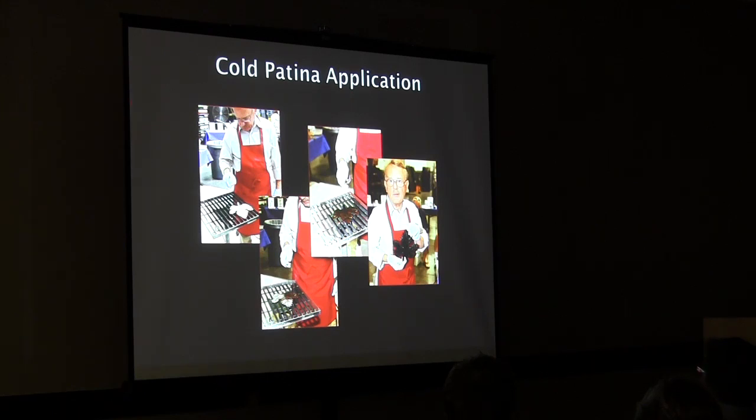And Black Magic is kind of nice because it's one of the many blacks, but it doesn't rust as quick. One of the things on steel and iron is that within 30 minutes to 2 hours, you've got acid combined with selenium. Those are the 2 main ingredients in any of your blacks. And so the selenium turns it black, but the acid that's making it bite starts to rust it. And so you don't have a lot of time.